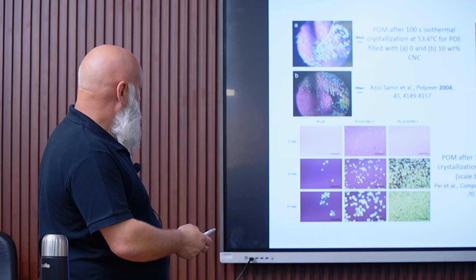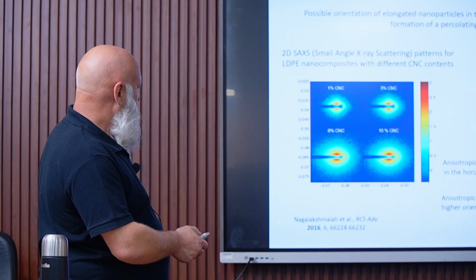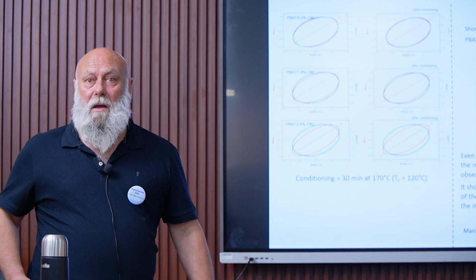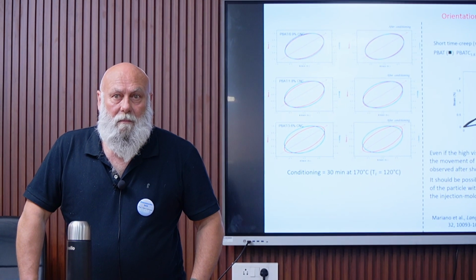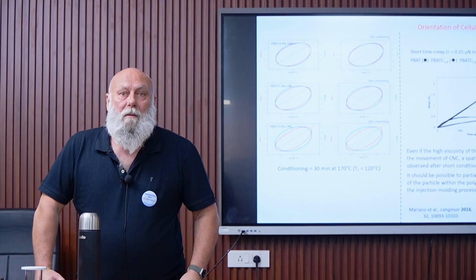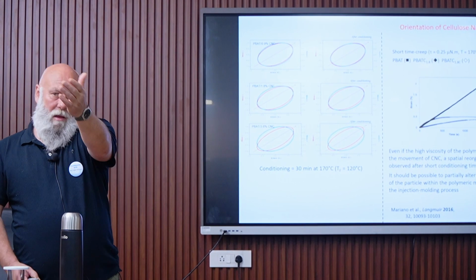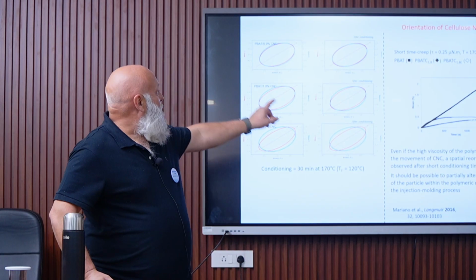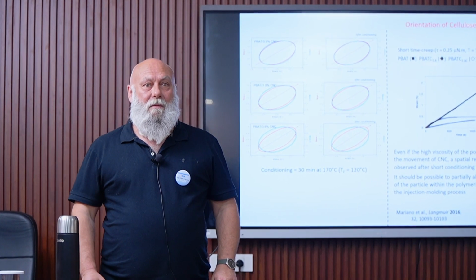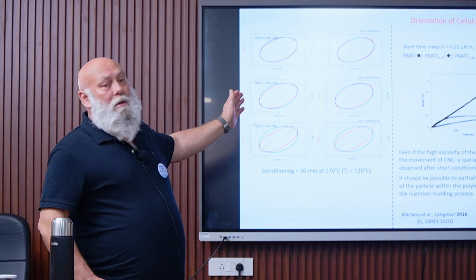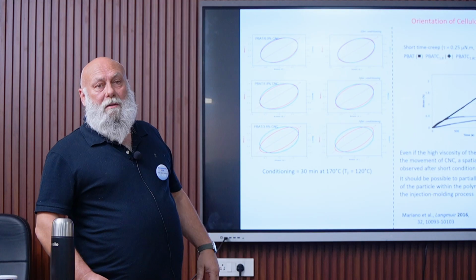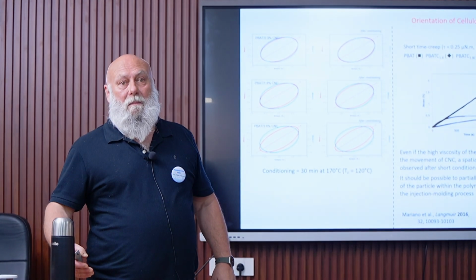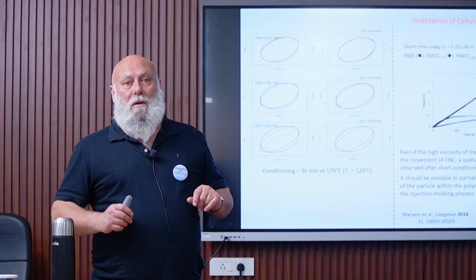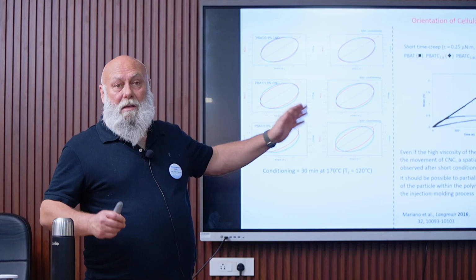Sir, in the case of the creep test, the temperature you mentioned, 170, in that composite. The creep test, yes, last slide, I think. In the case of composite, how can we fix the temperature? How can we determine at which temperature we have to do the creep test? In fact, we use this temperature because we want to see what happened in the melt, because we are interested in melt processing. But this experiment can be performed at any temperature.